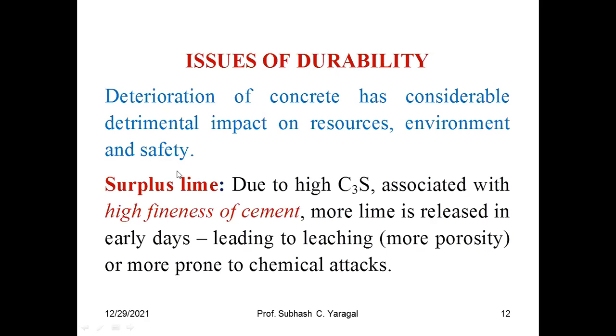One is the surplus lime. Please understand, due to high C3S, which is associated with high fineness of cement. So finer the cement, more is the production of C3S, one of the constituents of hydration of the cement. More lime is released in early days, which leads to leaching. Leaching means this lime would like to come out of the body of your concrete. So if this leaches out or tries to come out, it is making the body of concrete more porous, or you are increasing the porosity of the concrete element. Structural element could be a beam, column, or a slab. So you are making that more porous.